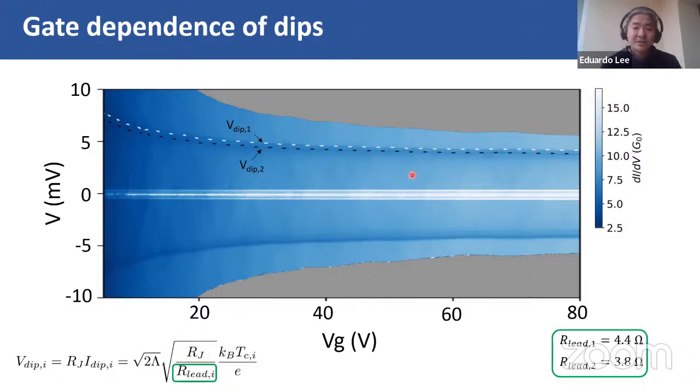So then we see these two dips, and over here, the only other parameter that we can change is indeed the normal resistance of the leads, and this is what gives this slight asymmetry. Now, to grow confident that this is indeed the case, we started making asymmetric devices, and that's what I mentioned later on, that we made it on purpose. The different lengths of the two leads was actually to check that this was indeed the case, and this device in particular is quite symmetric. That's why both dips are almost coinciding on top of each other.